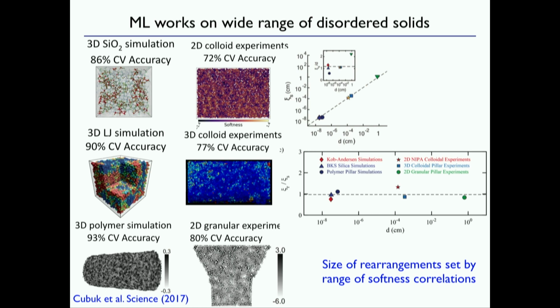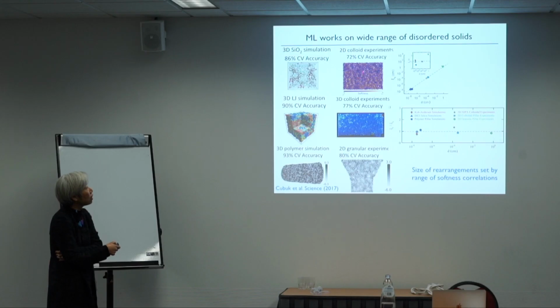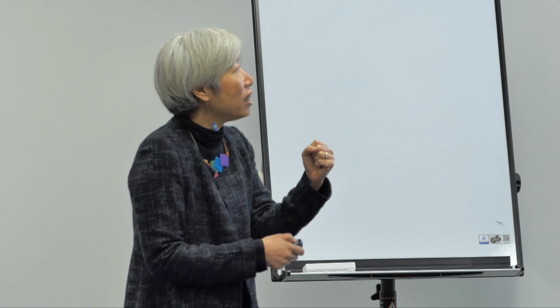Okay, so I'm going to skip the last story, which is the story of plasticity. Just to show you that we looked at systems from covalently bonded silica to 2D colloid experiments, 3D colloid experiments, simulations of Lennard-Jones, simulations of polymers, and experiments on grains. And in all of these, we analyzed softness. We found that the range of correlations for softness, divided by the size of a rearrangement, was 1 across all these systems. That says the reason rearrangements are localized in these systems is because the softness is correlated on the scale of a particle. It has short-range correlations. That's why the rearrangements are localized. And the vertex model actually falls right on there as well.